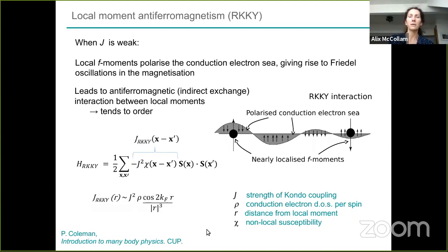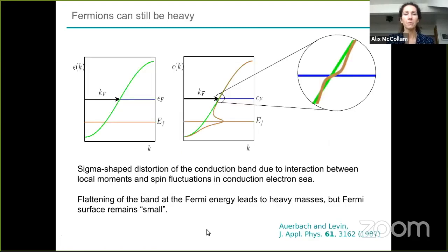So when you're in the weak J limit, you still have a renormalization of the conduction band, but it's different. So the renormalization of the conduction band in the case of the well established Kondo effect, and the weaker J when you don't have the Kondo effect, but you have this antiferromagnetic or the indirect coupling between the local moments, it looks as the following. So this is the unmodified band structure.